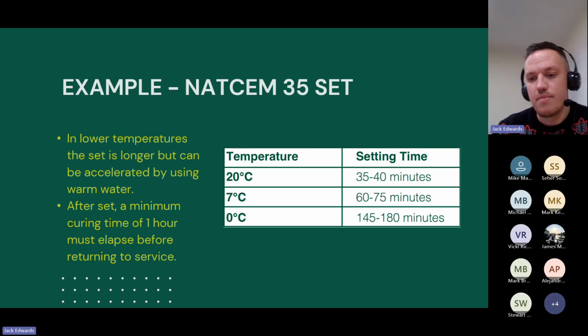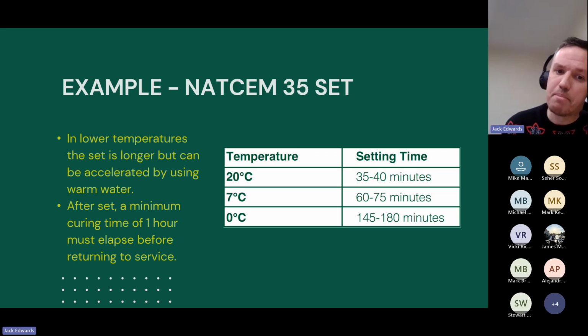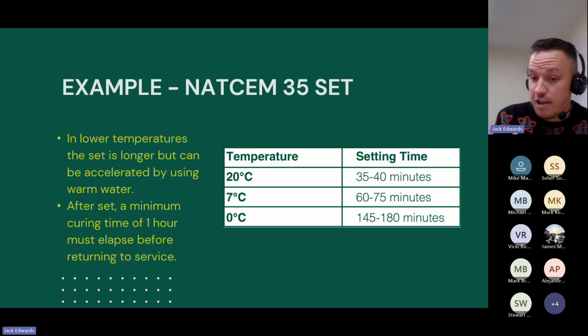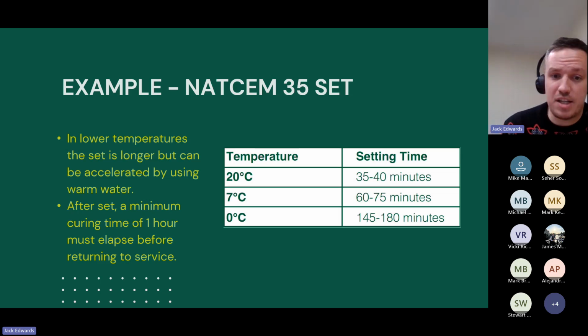So we used to have all the setting times and the strength gains, everything in the document was always based on 20 degrees. But we've now included a table that you can see on this slide to show the difference in how the temperature will affect the initial setting time. So you can see on this particular slide, for instance, we're looking at 7 degrees, setting time between 60 to 75 minutes for our NATCEM 35, which is called 35 because it sets up to 35 minutes, but that is based on 20 degrees, as you can see, 20 degrees lab conditions.